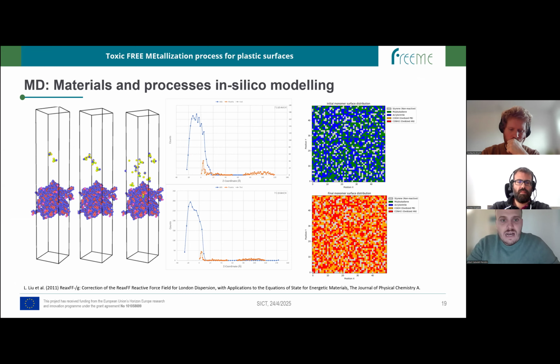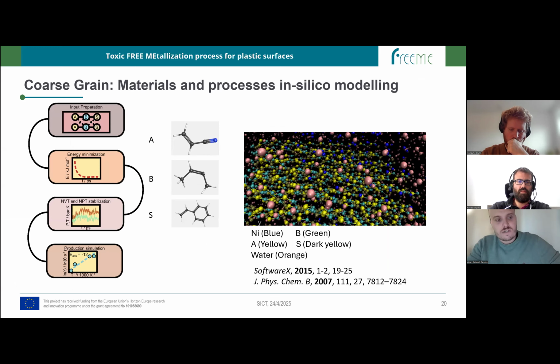Okay. Then we also were, as I said before, generating coarse grain simulations. In this case, we are not working with the etching. We are working directly on the deposition, okay, of nickel on the ABS substrate. Okay, so to do so, we generated this workflow that actually is fully automated, written in Python and Bash, and using GROMACS as the coarse grain simulation software.